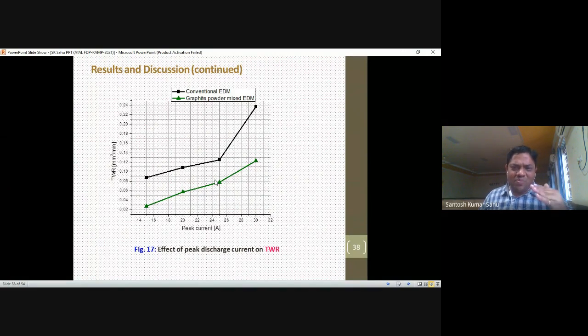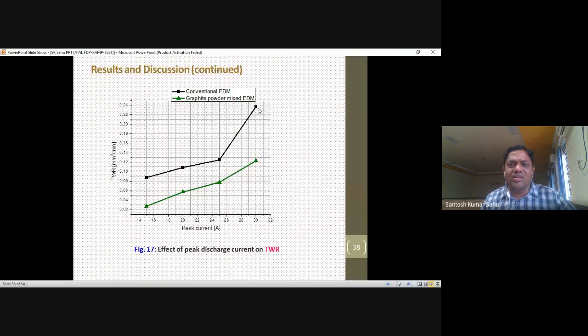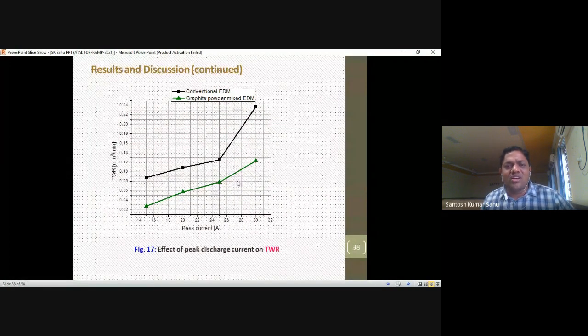Again, you can see in the black line how the TWR, the wear rate of the tool in the EDM, deteriorates. It is not smooth. You can see from 15 to 20, then 25, again unevenly in 25 and 30. So the line is not smooth. From that we can conclude that roughness can increase and material is lost from the tool. So we can save our tool by adding graphite powder in our EDM, and whatever tool wear there is, it should be smooth. The wear should be minimal, but you have to get smooth wear.